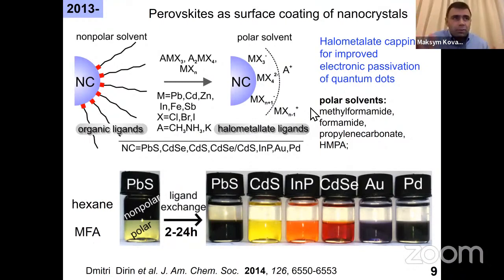And so back then, in 2013, we understood that inherently halides make for a good semiconductor. So why don't we use them now as a coating for conventional quantum dots? So we take a perovskite as a shell to coat the conventional quantum dot instead of using the core shell strategy. And so that was super exciting because we were able to use these soluble forms of these perovskites, they are called halometalates, to use them as a surface capping ligand. So we displace organic ligands, we cover the surface with this halometalate coating.